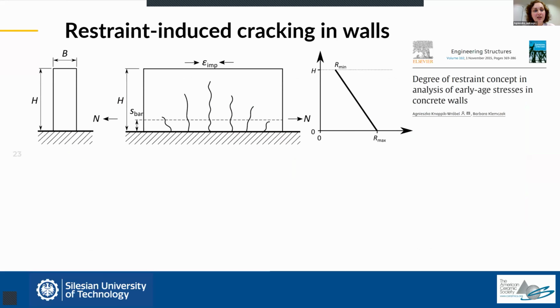So again, here you see a wall with a typical cracking image. And as we have explained, the height of the cracks will depend on the effect of base restraint. And this is usually depicted with the use of the so-called degree of restraint. And I think it also can be explained rather naturally. So the biggest restraint, so the force, let's say, with which this wall is held, it is biggest at the joint, and then it decreases towards the free top of the wall.